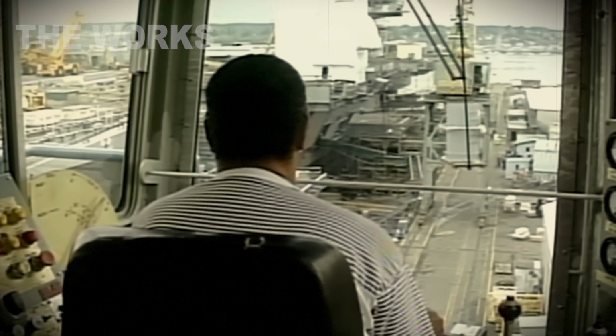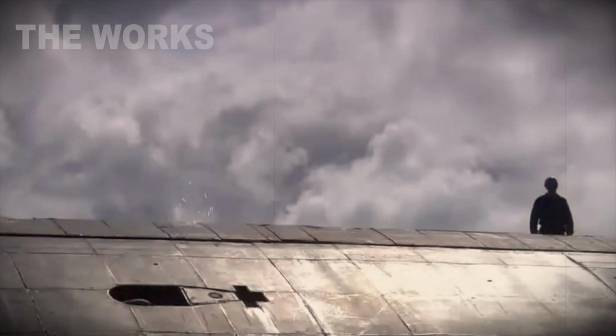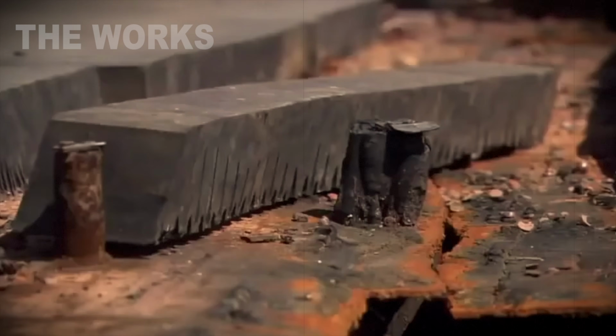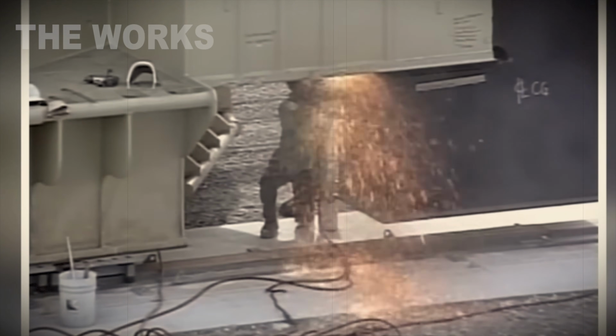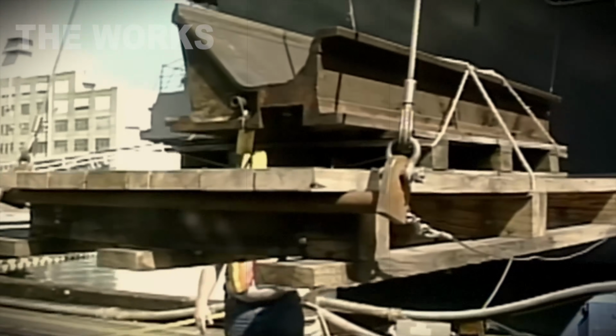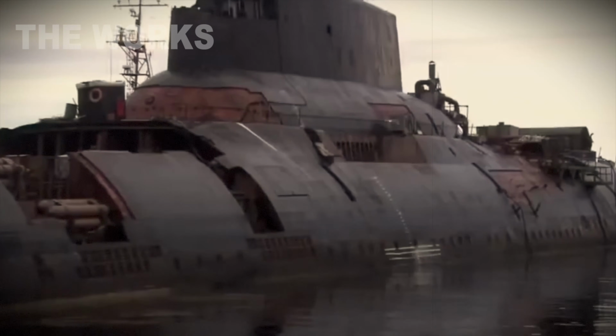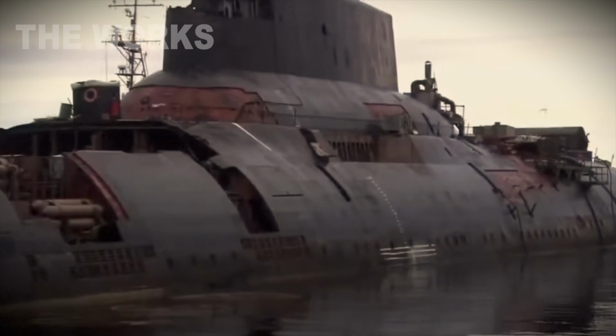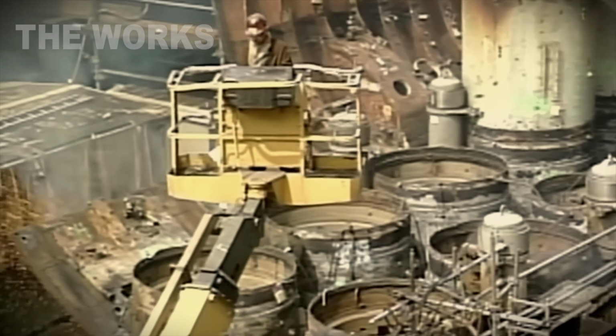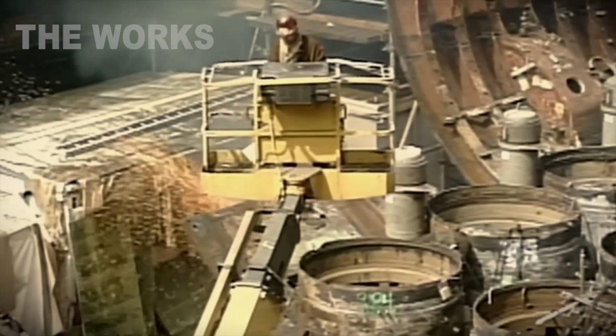You get a cylinder. All technological openings are welded shut with half-inch steel plates. Welding, electric arc, 1/4-inch diameter electrodes. Current, 350 amps. You get a sealed capsule. It's lifted by a 200-ton crane and loaded onto a barge. The barge is towed to a burial site.